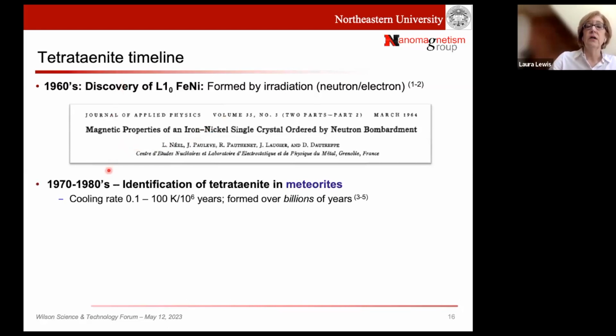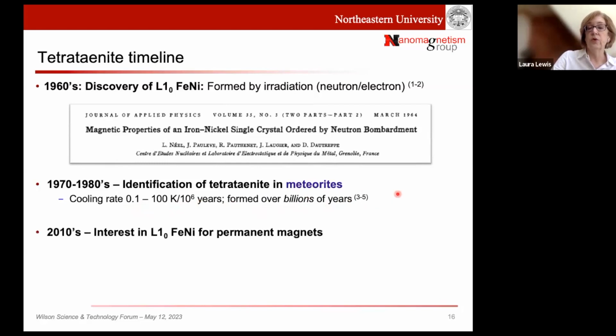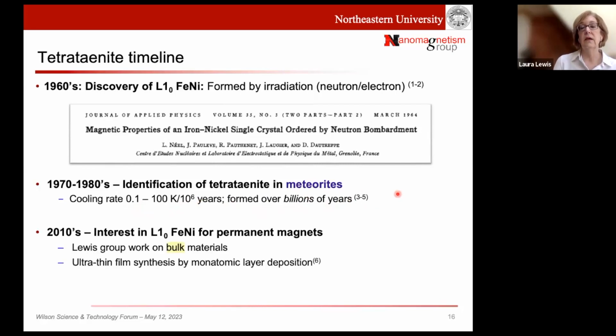Now, nothing happened until at least 10 to 20 years later, where meteorite scientists, meteoriticists, started to find this order in meteorites, and these were formed over billions of years because they need to form this structure. They need a cooling rate of 0.1 Kelvin per million years to 100 Kelvin per million years. This is what's in the literature. And after that, in the 2010s, people started to think, I wonder if we can develop this for permanent magnets. And primarily, the players in that field were my group, and I was working on bulk materials. I call them bulk because you can hold them in your hand, and they're available for engineering purposes.